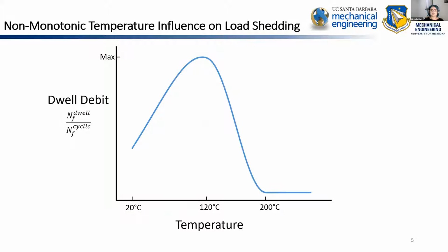Load shedding is also dependent on temperature, where whenever you run your dwell experiments and your cyclic fatigue experiments at room temperature and compare those two results, you have that dwell debit. If you increase the temperature and run those experiments at about 120 degrees C, you see a maximum where there's the greatest disparity between your dwell lifetime and your cyclic lifetime. But as you continue to increase that temperature up to about 200 degrees C, you no longer have a dwell debit. Your dwell lifetime and your cyclic lifetime are essentially the same.